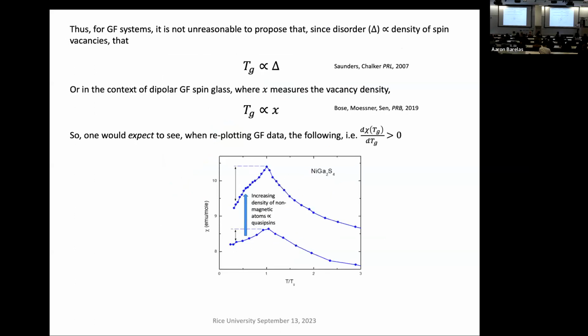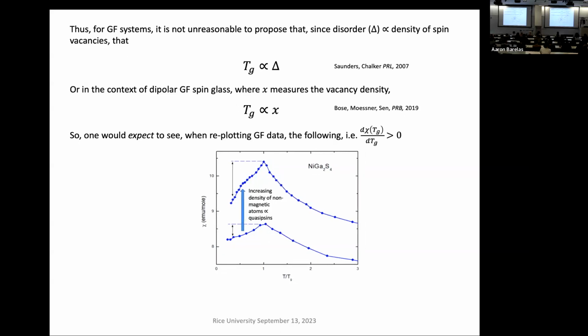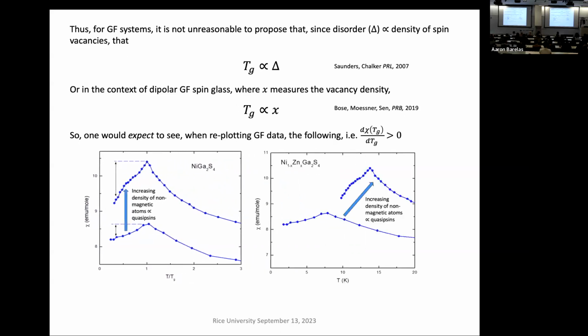So for GF systems, it's not unreasonable to suppose that since disorder, which we'll just call delta, is proportional to the density of spin vacancies, Tg should go like the density of spin vacancies. Or in the context of the dipolar spin glass, as considered by Bose, Moessner, and Sen, Tg should go like x, where x is the vacancy density. So one would expect to see, when replotting this data on a non-normalized scale, something like this. That's what we would expect to see if this were like europium strontium sulfide, a conventional spin glass.